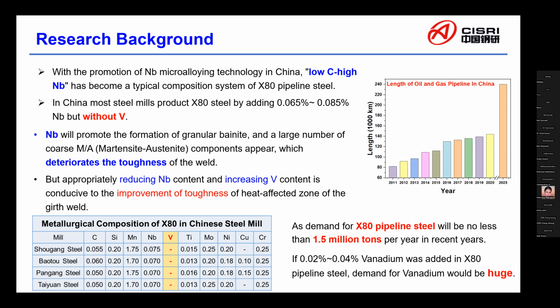China began to promote the use of X80 pipeline steel on a large scale in the second West-East Gas Transmission Project in the year 2009, with the application of niobium microalloying technology. Low carbon and high niobium has become a typical composition system of domestic X80 pipeline steel. However, high-grade pipeline steel made in China doesn't contain vanadium. As an effective grain refining element, niobium plays an important role in the strengthening of pipeline steel. In China, most steel mills produce X80 steel by adding 0.065% to 0.085% niobium.